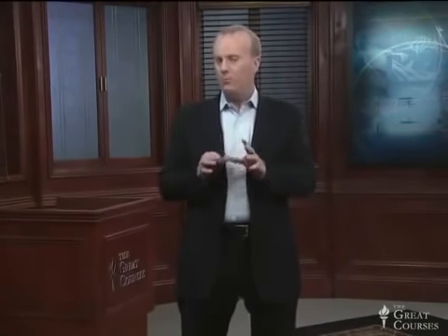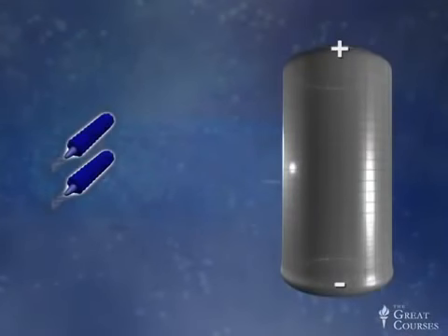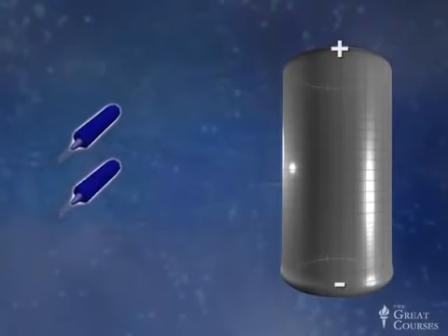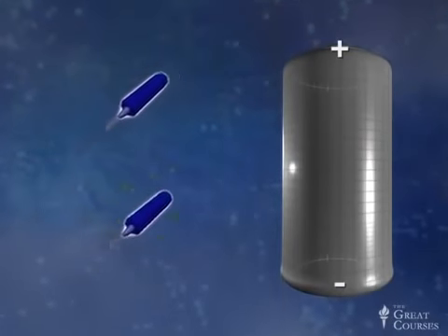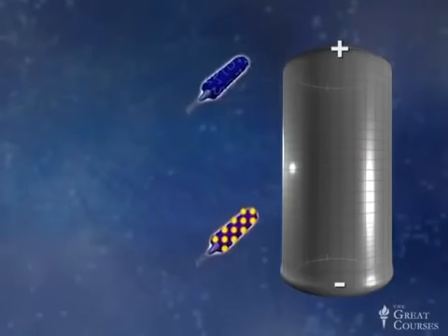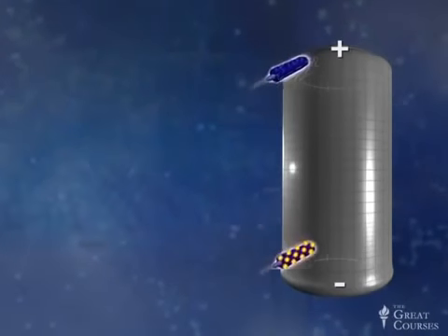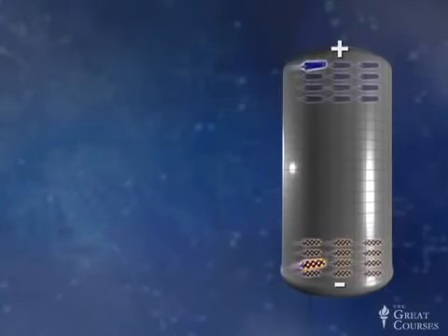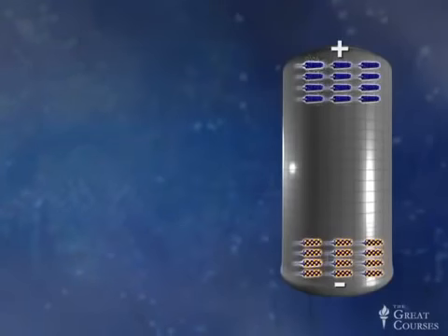The other building block that they needed was something to make these more conductive. And so the researchers found a way to put an additional peptide, so an additional protein, on the surfaces of their viruses, to make a kind of, they called it a bifunctional virus, something that could enable them both to grow the cobalt oxide nanoparticles, which were crucial to the battery function, but also be able to grow gold nanoparticles that led to a dramatic improvement in the conductivity of these devices.